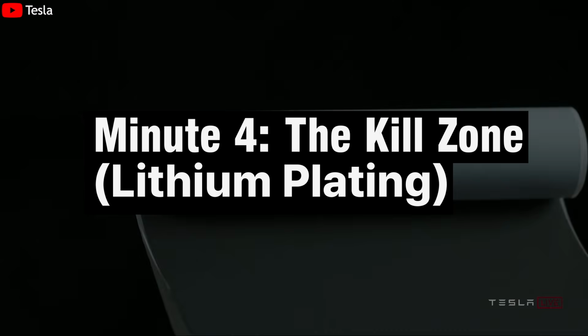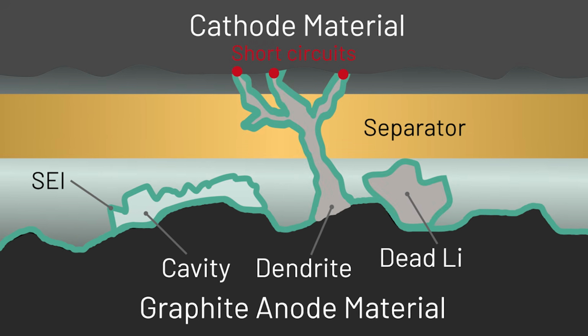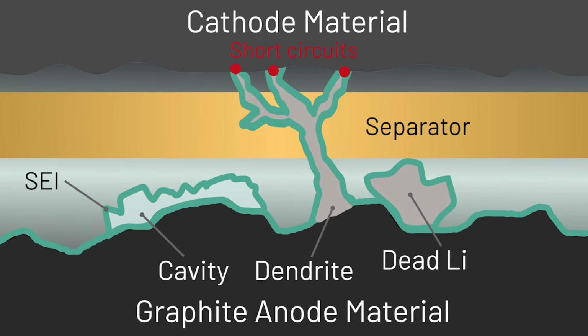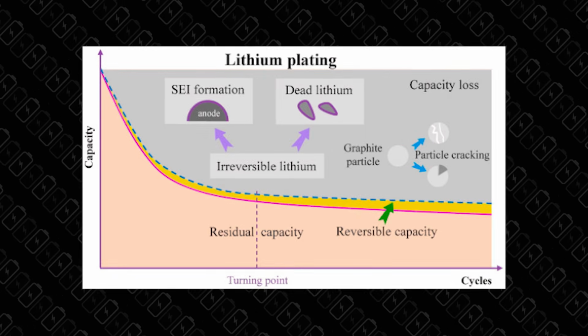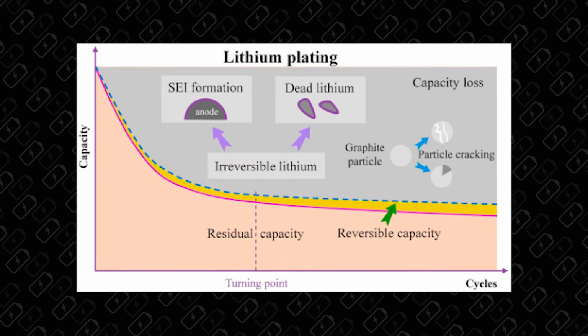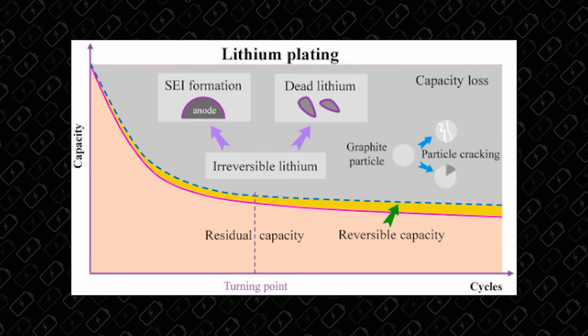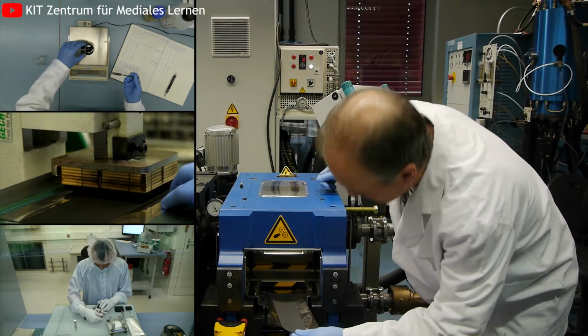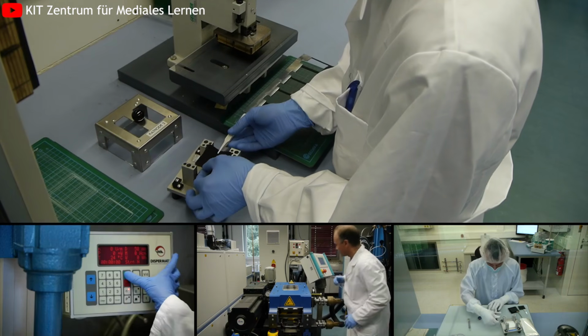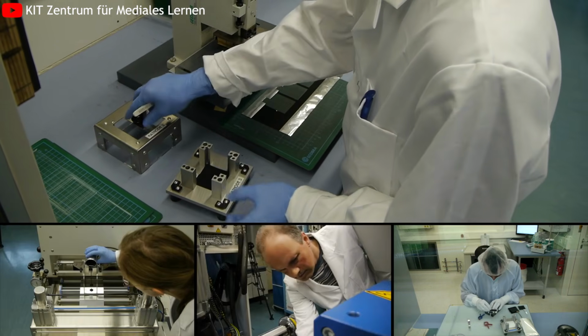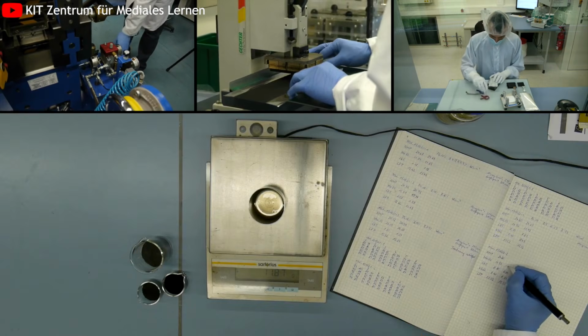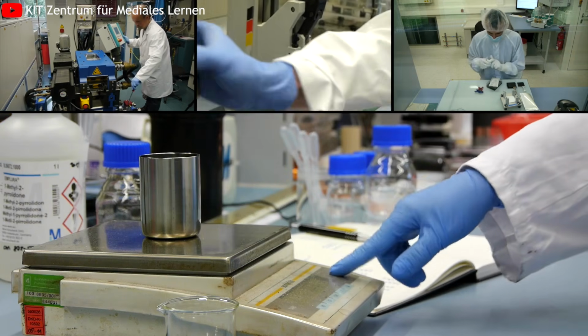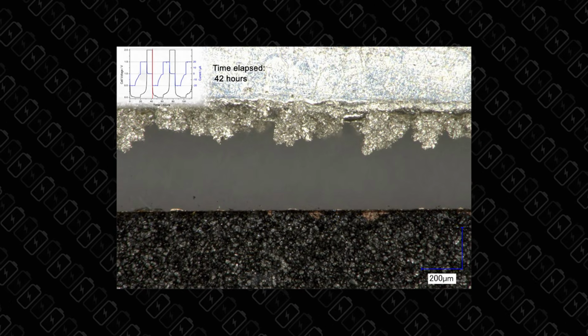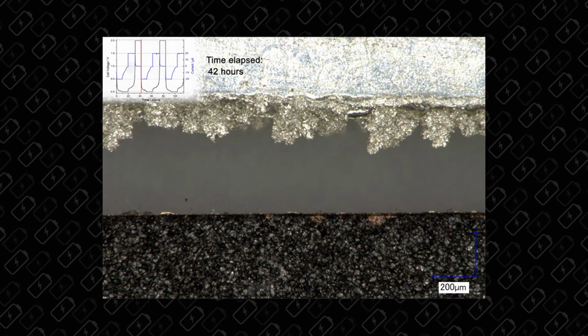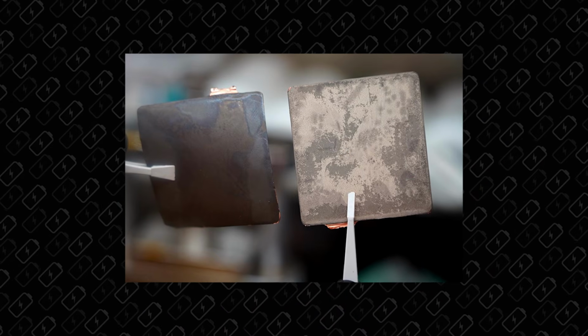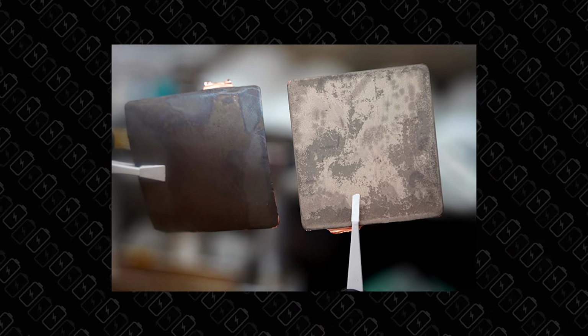Minute 4. The kill zone: lithium plating. Minute 4 is the most dangerous phase, the kill zone, where lithium plating begins. Plated lithium is not harmless. It is dead capacity. Over repeated 5-minute charges, it grows into mossy, needle-like dendrites. A startup might show one successful demo, but they will never show you the cross-section of that battery after 50 cycles. The anode will likely be coated with inactive lithium metal, permanently reducing range. Worse, dendrites can puncture the separator, causing internal shorts and thermal runaway fires. This is the hidden cost of extreme fast charging. You are electroplating the inside of the battery with dead metal.